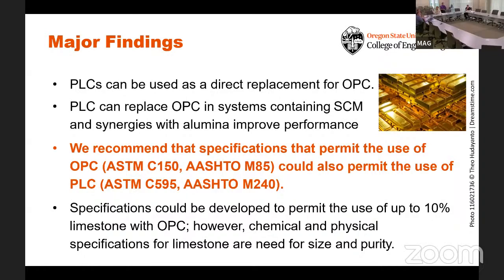And they also mentioned that specifications can be developed to allow for an OPC with a blending of limestone. That also works, but they need to make more specifications to confirm that the size of the limestone and the purity of the limestone is up to speed. Most of the plants have X-ray diffraction and analysis, and they know the purity of the limestone. And when it goes into the ball mill, everything is underground. So they were just saying it seems it can be done at a batch plant if you're going to blend limestone, but not quite there yet.